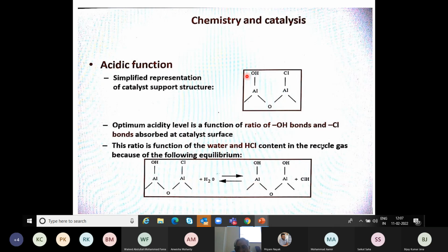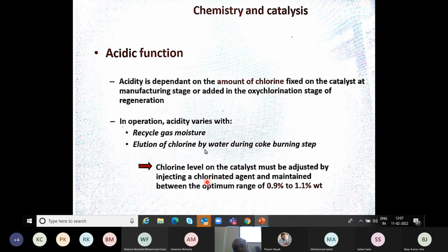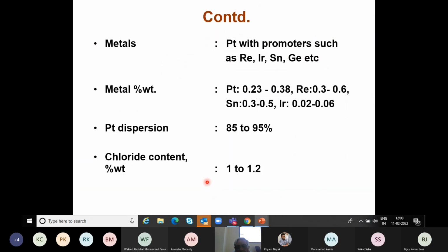So this is of course a simplified representation of the catalyst support, and we try to optimize the balance between OH and Cl in order to make sure that we have the desired amount of acidity. And also the moisture in the feed is minimized. It's almost bone dry feed, so that we don't reduce the chlorine present on the catalyst. But nonetheless, as the reaction continues, the chlorine leaches out, and so we keep on replacing that chlorine by adding a chlorine containing hydrocarbon.